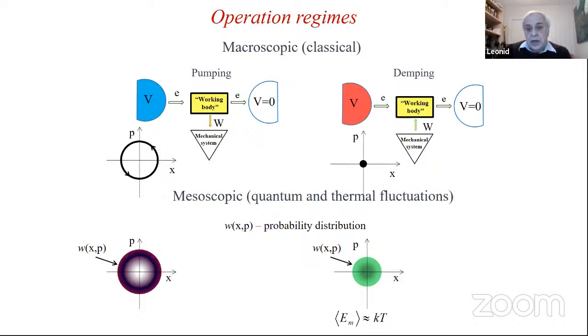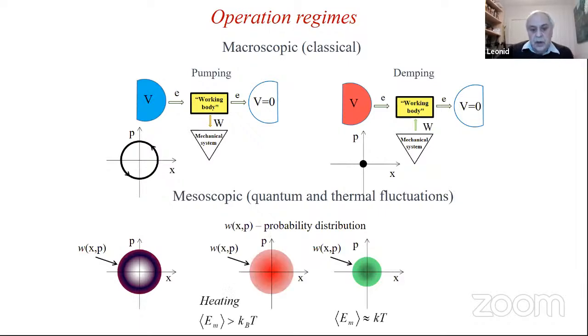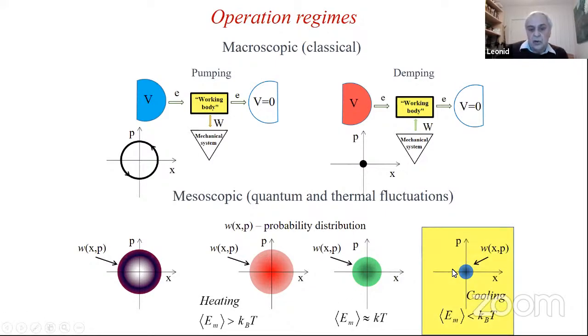But in our case, when we connect to the non-equilibrium subsystem, which is not in equilibrium, we have two possibilities. Maybe the average energy will be greater than the temperature, and in this case we can speak about heating, but it might also be much smaller than the external temperature. And in this case, we will speak about cooling of the mechanical system. And this is the most interesting regime of behavior of a mechanical system in a nanoelectromechanical situation. Of course, from these three, it's most interesting this one, and we will focus on this situation.